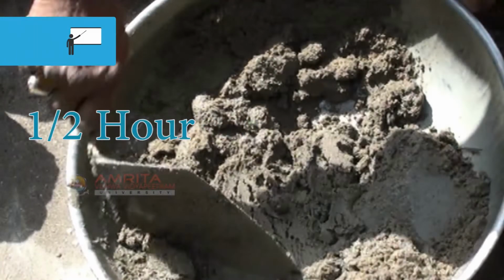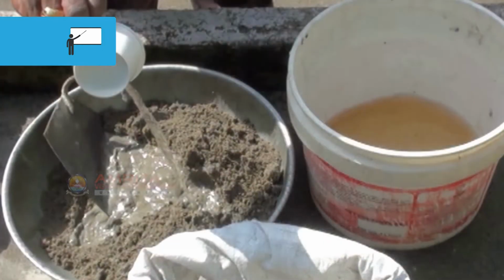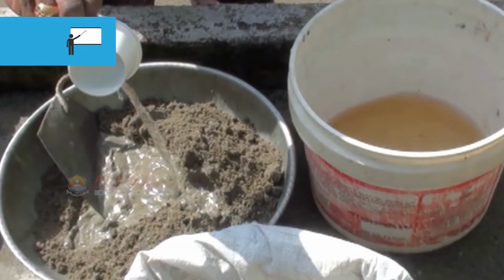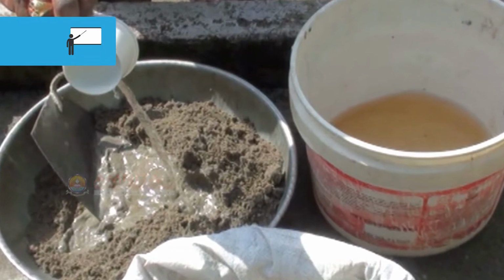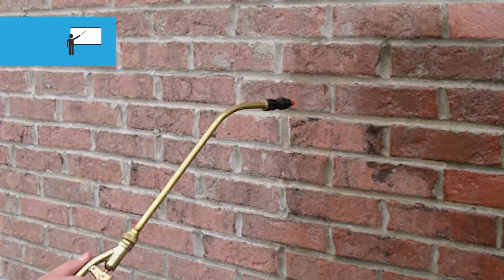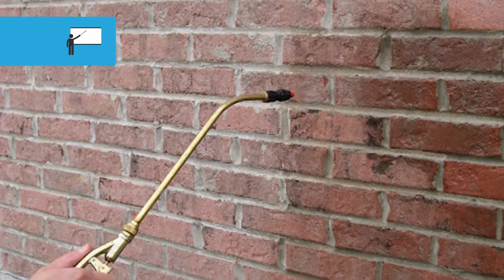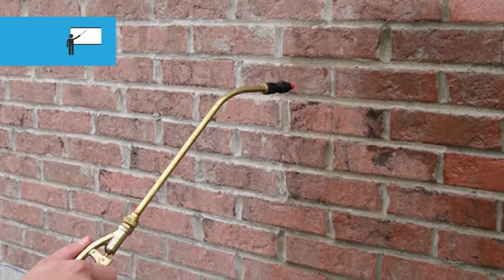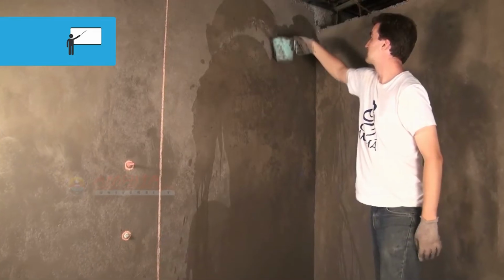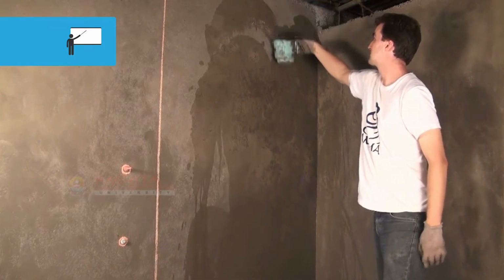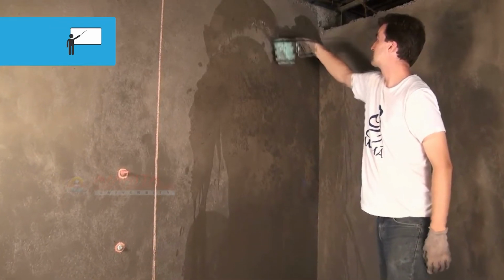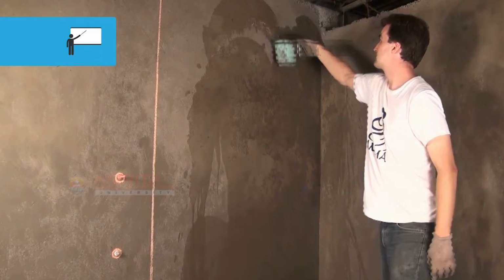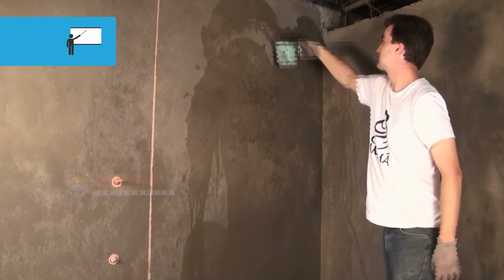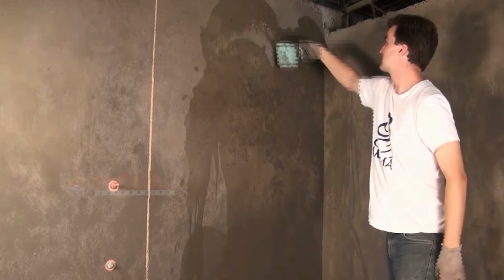After adding water, the mixture has to be utilized within half an hour. Water should be added to help the mortar in the process of setting. Before applying mortar, the wall has to be dampened. After applying mortar, the area should be kept damp or wet by sprinkling water for at least 7 to 10 days to avoid rapid drying of mortar.